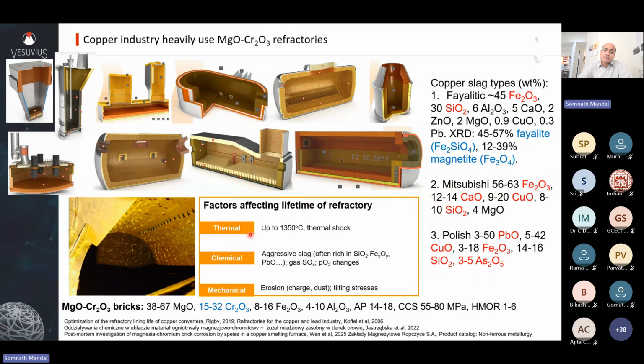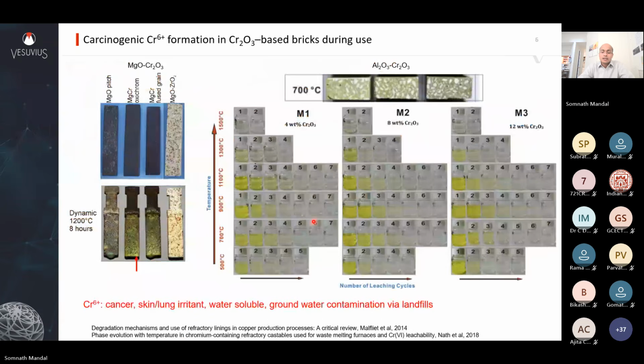So one of the wear mechanisms is thermal shock, because you go from batch to batch and you wait in between where your furnace cools down a bit, and a big majority of these furnaces are water cooled. So especially in the slag line, you end up cooling it pretty fast if you have a discontinuous supply of hot metal coming in. And then there is, of course, erosion due to charging of the materials into the furnace, and then there are tilting stresses, and then I've talked at length about the corrosivity of these slags. And one of the other things that is really corrosive about these furnaces is that in the upper portions of the furnace you have a lot of SO2 gas, and this gas is highly corrosive to refractories. It forms sulfates and causes volume expansion.